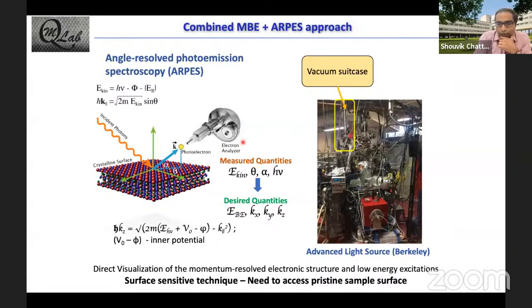But we can also get an idea about the electronic structure very directly by utilizing this technique of angle resolved photoemission spectroscopy. For those of you who might not be very familiar, this is basically a spin on Einstein's photoelectric effect. So what we are doing here is that we are coming in with an incident photon light and kicking out a photoelectron. And now if you can measure this photoelectron, its kinetic energy and angle at which it is coming out vis-a-vis some particular crystallographic direction of your crystal surface, then by utilizing the standard energy and momentum conservation principles,